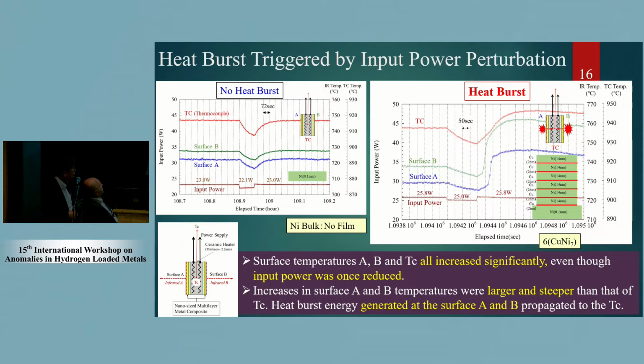Okay, this is a typical result of an intentionally induced heat burst. In this case, we use copper nickel standard 1, and the input power is here. At the beginning of the experiment, we applied 25.8 watt and slightly decreased it and went back to the original value. Okay, and after that, at this point, a heat burst occurred on surface B, and after that, at this point, a heat burst occurred on surface A, and they propagate to the center thermocouple here, like this.